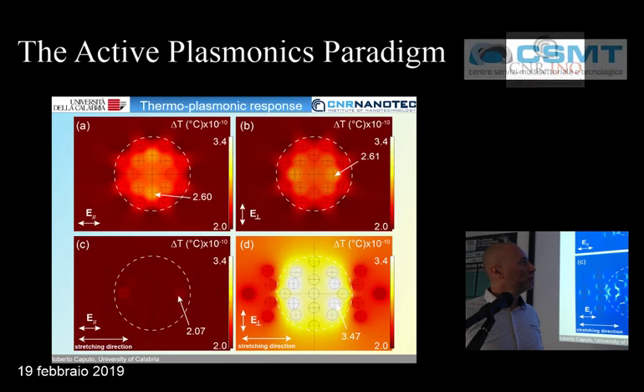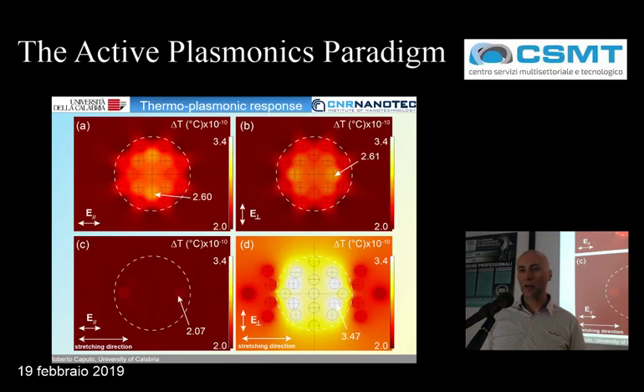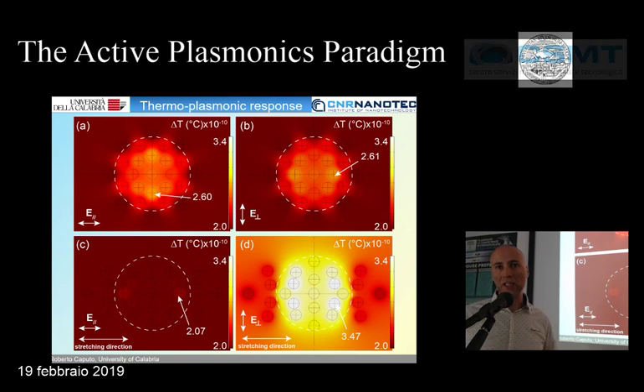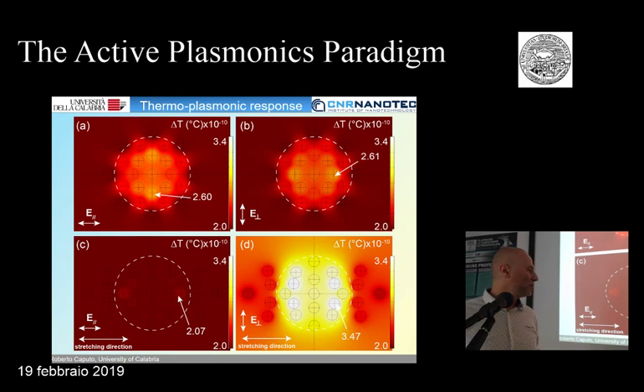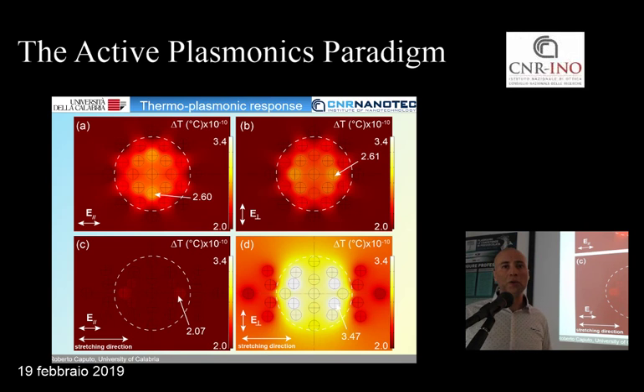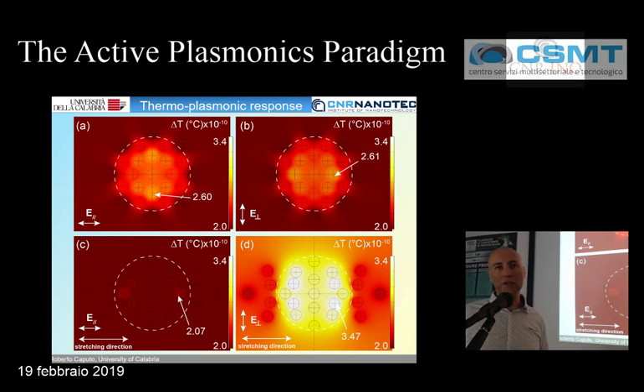But when we move to the thermal behavior of the system in the same conditions, so at rest or under stretching with different polarizations, you can see indeed a very high increase of local temperature in the stretched condition. This confirms that in the experimental case, when you stretch, you have a general increase of temperature of the sample.